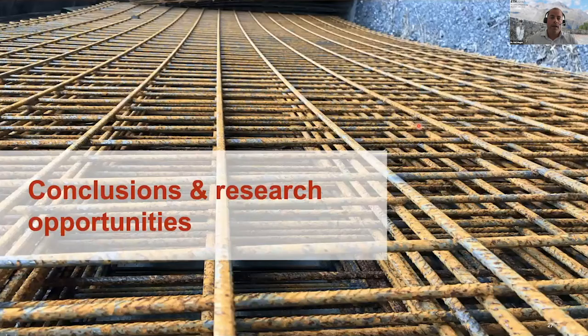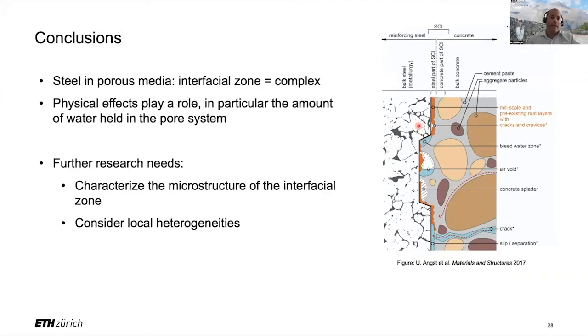Now, let me conclude by saying that corrosion of steel in porous media is complex because we have a complex interfacial zone. In addition to chemical influences of the electrolyte present at the metal, physical effects also play a role, in particular, the amount of water that is held in the pore system. So to better understand all of this, there is a need to better characterize the microstructure of this interfacial zone, and we have to consider the very pronounced local heterogeneities at the steel-concrete interface.